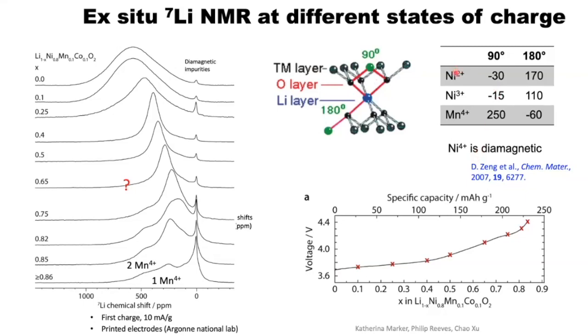If you have a nickel 2+ ion with 2 eg electrons, you can have different shifts depending on whether the nickel points directly at the lithium via a so-called 180-degree interaction or 90-degree interaction. This is nicely described in Dongli Zeng's work a number of years ago. But basically, if you're a lithium and you see nickel 2+, nickel 3+ and nickel 4+ randomly distributed, you get this very broad pattern that we can model using close to random distributions. Interestingly, when you start to pull the lithiums out, you can see a noticeable narrowing of the spectrum. And at the top of charge, you see much more clearly resolved peaks.